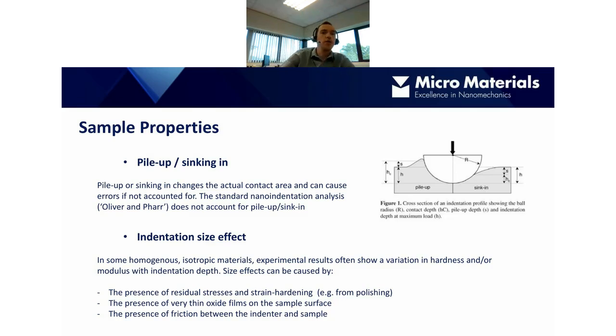And also indentation size effect. So in some materials, we often see an increase in hardness near the surface, which is not due to any sort of errors in indenter geometry or calibration. This can be due to a number of factors, such as the presence of residual stresses, strain hardening, as I mentioned previously, from polishing perhaps, or the presence of a very thin oxide film on the sample surface, or even friction between the indenter and the sample. Okay. So as you can see, there are a lot of factors that we need to consider when performing nanoindentation